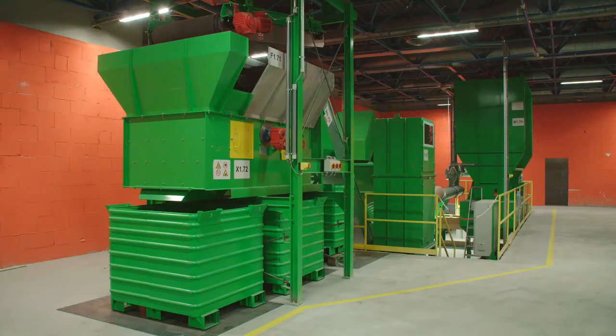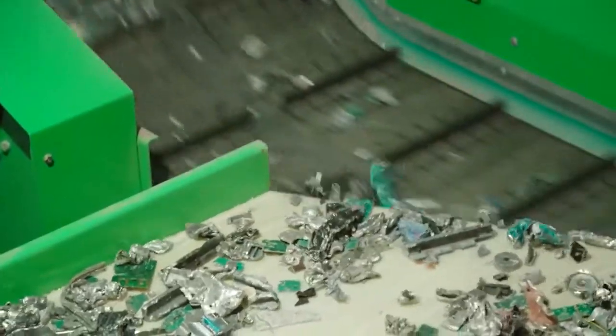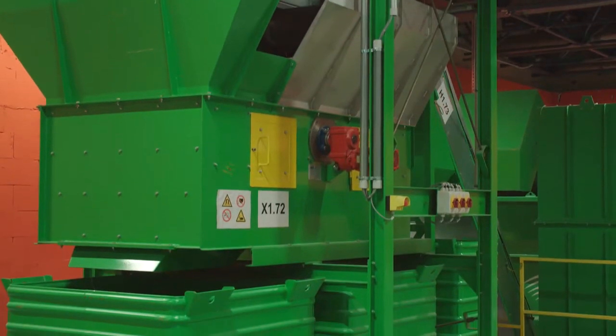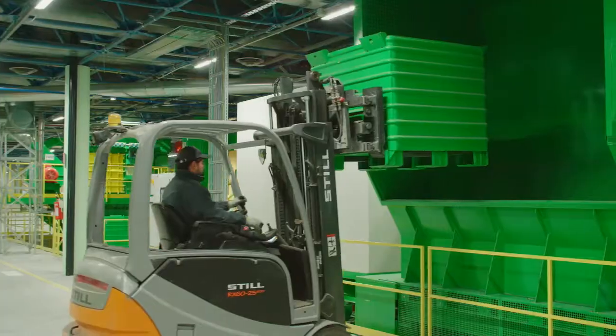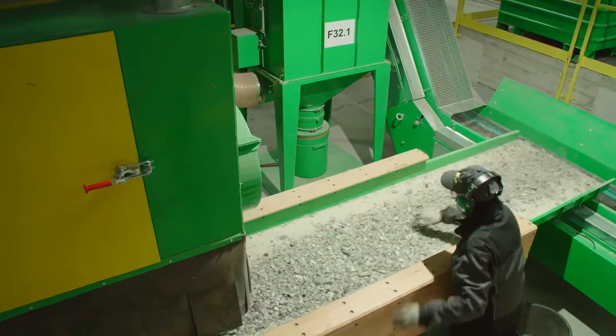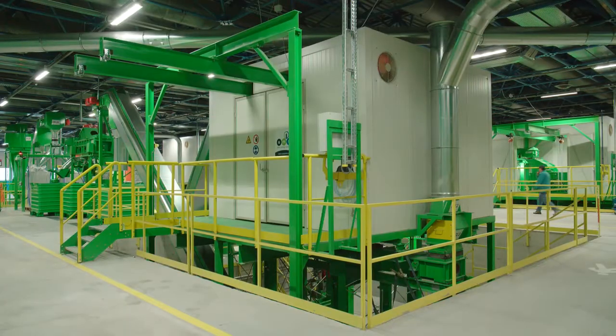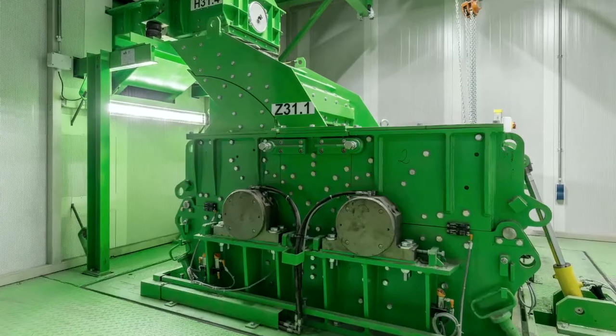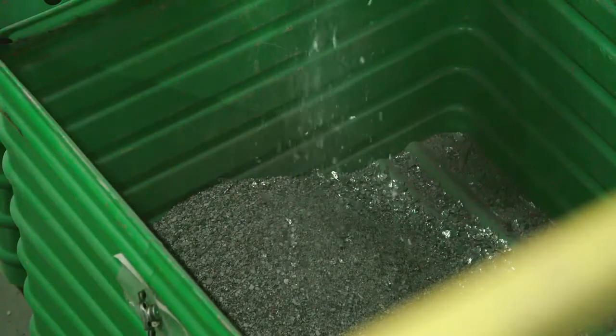A down-to-size shredder ensures the homogenization of size, which is a prerequisite for some of the following processes. It can also be the final step for metal or plastic fractions already marketable. Small parts, including valuable metals, are fed to the UMS proprietary double rotor hammer mill. Here the compounds are delaminated and transformed in grain shape and size when hammers drive them through the mill. Some metals tend to form balls, other metals remain flat, while plastics always remain flat. This enables further separation.